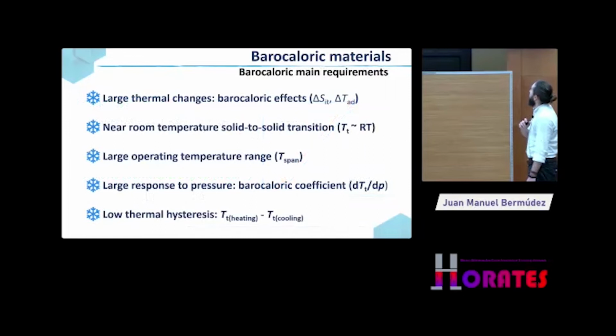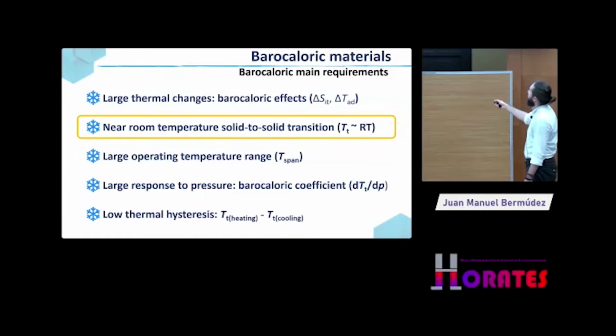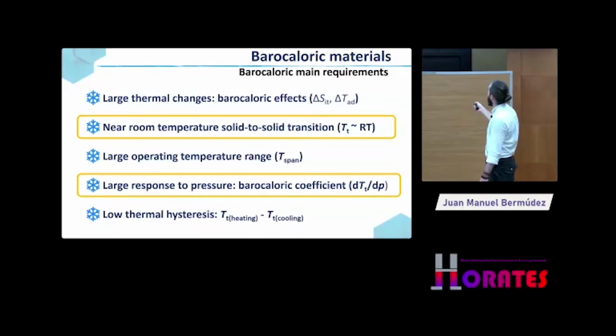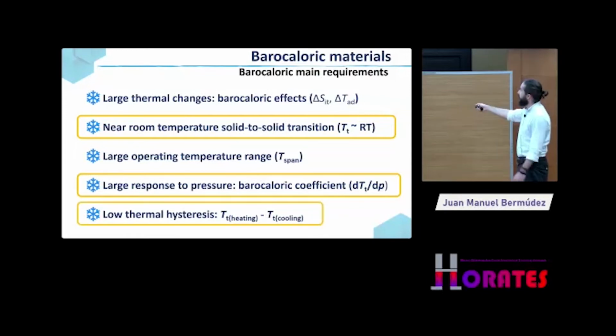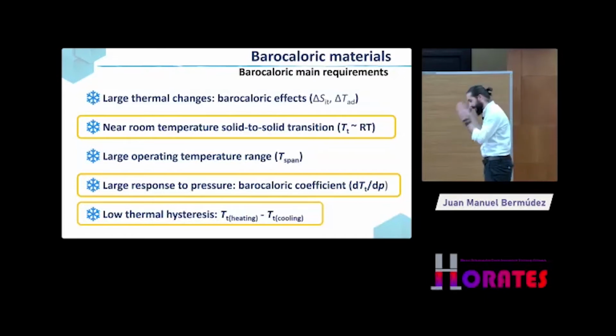Well, we have already talked about how to characterize the transition temperature of your material. We have talked about how to calculate the barocaloric coefficient and how this barocaloric coefficient impacts your efficiency, and also the same for the thermal hysteresis. How do we calculate the barocaloric effects here in terms of isothermal entropy change from those quasi-direct methods? And how do we calculate the operating temperature range, this temperature span in which your material can present barocaloric effects, in order to be able to be adaptable to different climates?